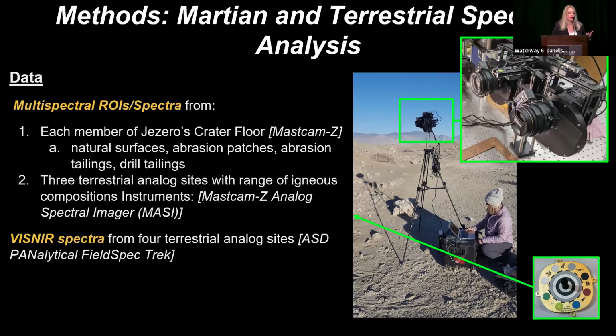That data is complemented by terrestrial analog data from 3 different field sites with a range of compositions that encompass what we observe in Jezero's crater floor. So they really range from intermediate to mafic. And we also used the MastCam-Z analog spectral imager, which is our analog to MastCam-Z built at Cornell University, to collect our terrestrial field data. And it was complemented by visible and near-infrared spectra from the ASD Panalytical FieldSpec, which covers a range of 350 to about 2,500 nanometers.